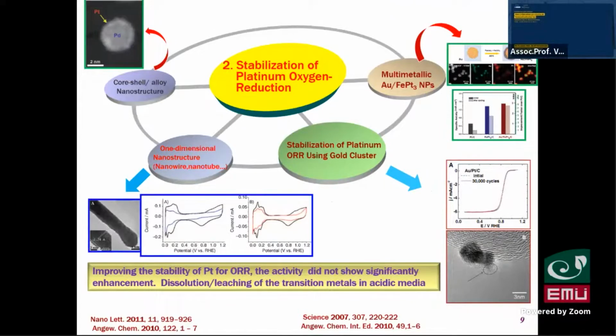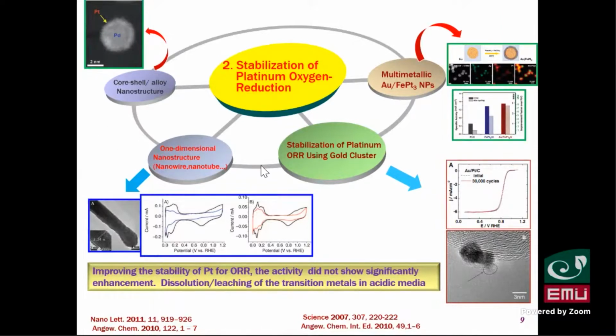So they also try to stabilize platinum for oxygen reduction by changing the morphology of platinum. Normally platinum catalysts are prepared as spherical particles around 5 nanometers, so to enhance stabilization, they change the morphology of platinum into 1D shapes, and they also use multi-metallic systems - not just binary alloys but three metals together - and also make core-shell nanostructures.